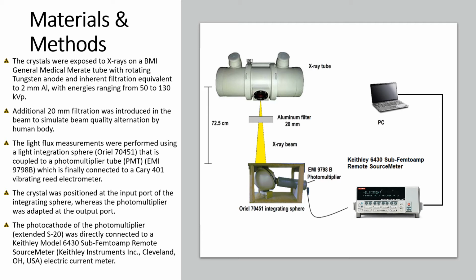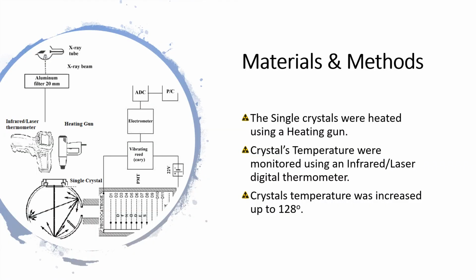The crystal was positioned at the input port of the integrating sphere, whereas the photomultiplier was adapted at the output port. The photocathode of the photomultiplier was directly connected to an electric current meter. In order to measure the absolute efficiency of the single crystals at high temperatures, a heating gun was used to increase the crystal's temperature to 128 degrees Celsius, as shown on the diagram on the left. The crystal's temperature was monitored using an infrared laser digital thermometer.